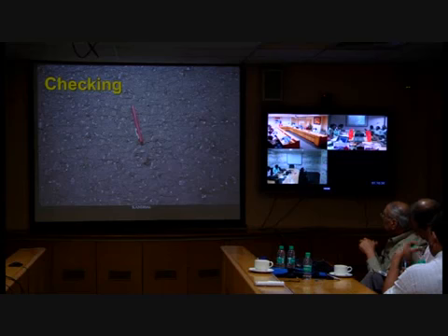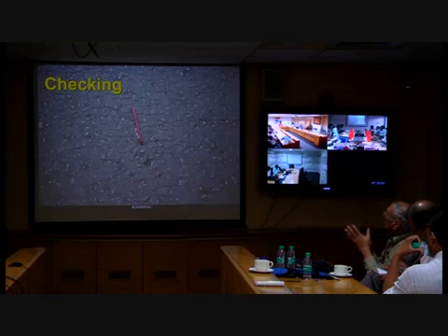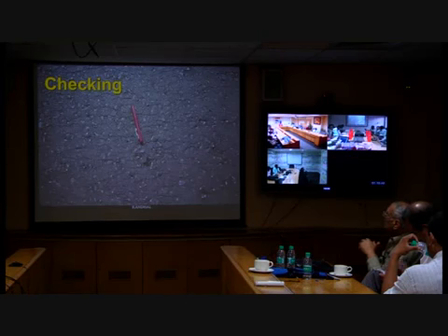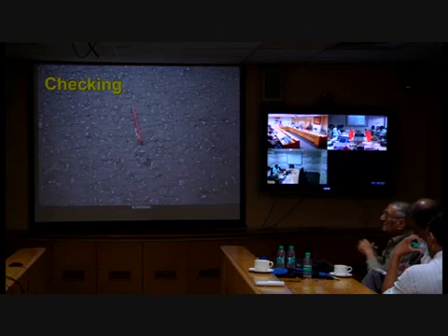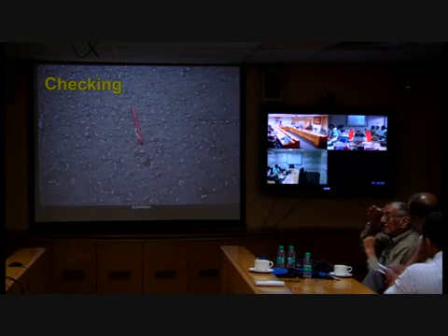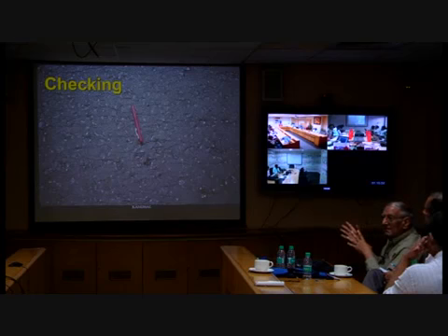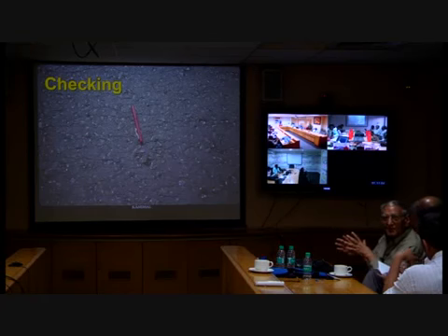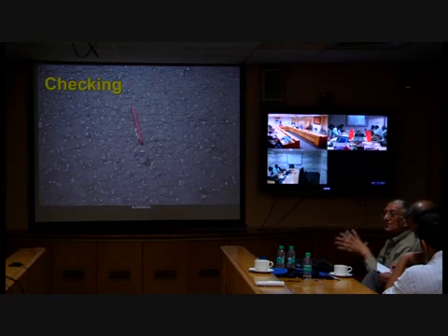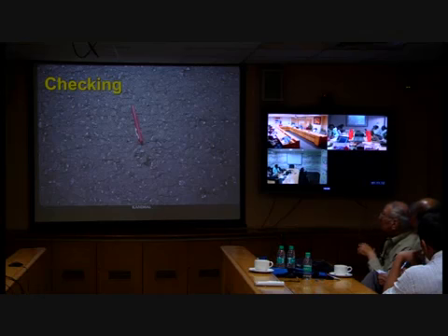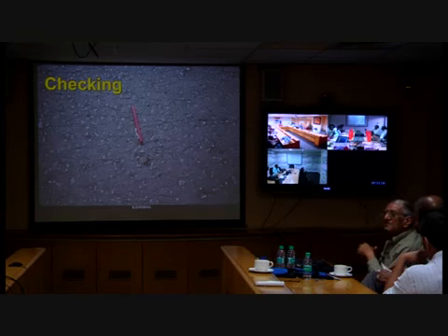So if this is happening at the time of compaction, I must do something about it. If I am using the vibratory compactor, I might have to do static rolling first, so the mix can carry the weight of the roller, and then turn on the vibratory. So many things can be done at the time of rolling. Nothing is fixed in asphalt. You have to do different things on different jobs. Somehow you have to change your rolling so you don't get this kind of checking. They call it checking in the US. Checking is nothing but hairline cracking resulting from the compaction.